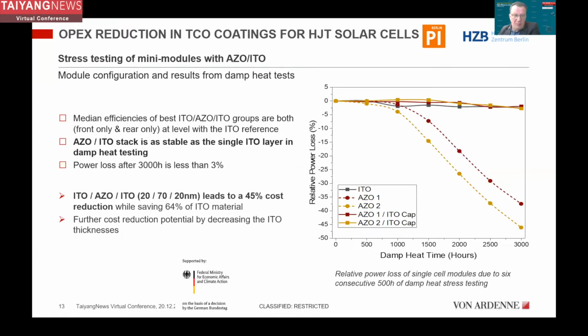There are materials out there like AZO, where you can reduce the cost dramatically. However, you also have to look at the long-term stability on the module side, and you see in this case standard AZO-coated heterojunction solar cells in a damp heat test, and you see a power loss after a couple of hours in the damp heat test.